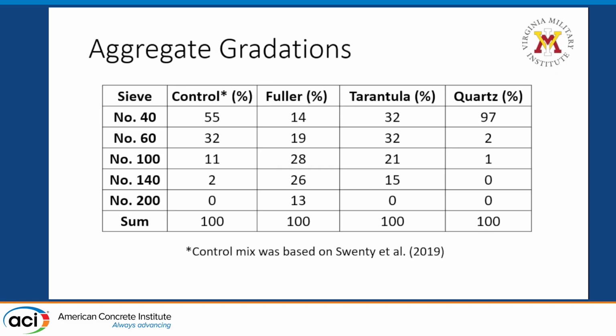These were the aggregate gradations used in these projects for the control baseline mix and the experimental mixes. The control mix was taken directly from outside, just the local sand found in Lexington, Virginia, where VMI is. The only manipulation to the control mix was removing all aggregates above the number 30 sieve and all aggregates smaller than the number 200 sieve. The 200 was the smallest sieve that we had.